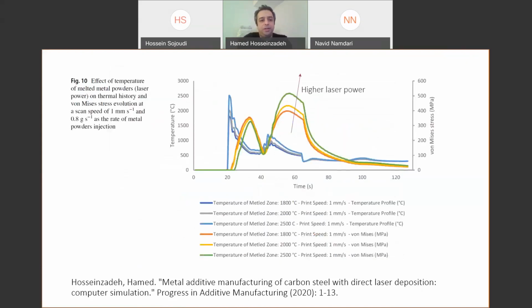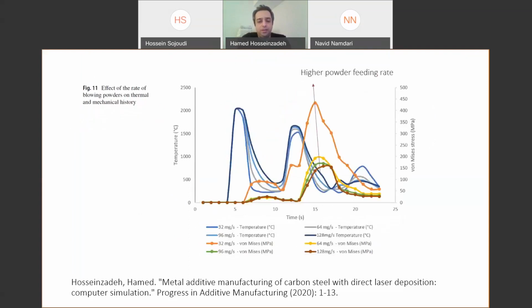Also, if we change the laser power, these are all for one sensor, and from that sensor we change laser power and keep the scan speed constant. You can see what would happen to the von Mises stress and also the temperature. If we increase the laser power, you can see we have a higher level of temperature and also stress in the sample.